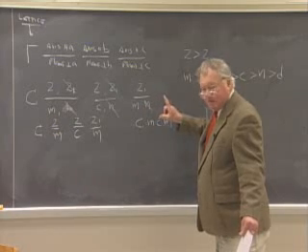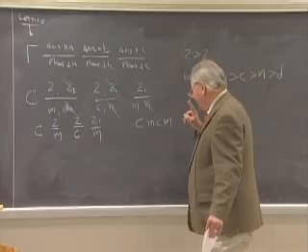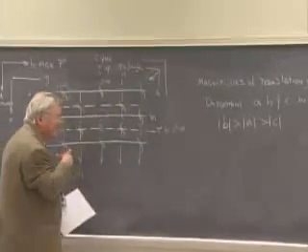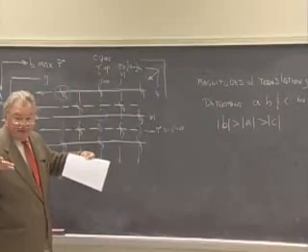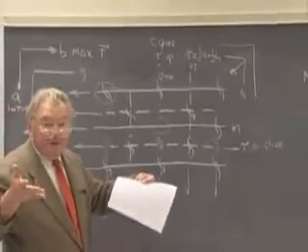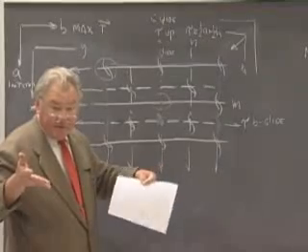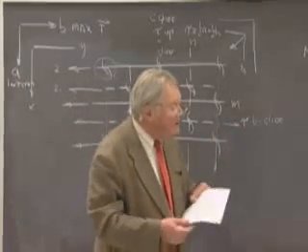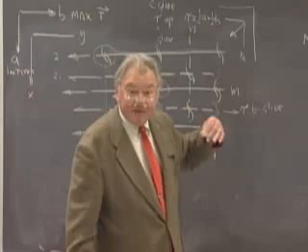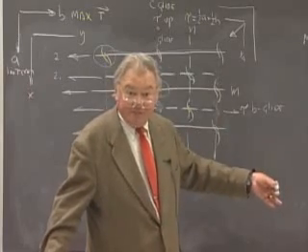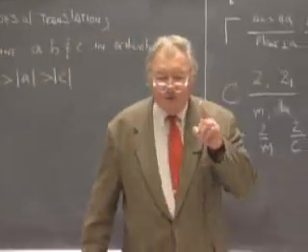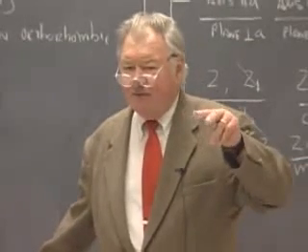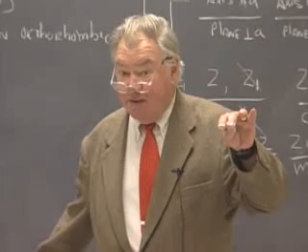Is it possible that two space groups could have exactly the same 3 symbols in the short form? And the answer is no, because if you think about it, you start with a lattice type. If you put a mirror plane in one orientation, a mirror plane in the other orientation, that really is all you have to specify in order to determine every other symmetry element that's present. You simply combine those operations, and you find that when you've taken these symmetries and rotations and combined them with the lattice translation, it comes out to one and the same, a unique result. So your question was, what happens if you take another 3 symbols? You end up with the same result. 3 of them really are enough to specify what the group will turn out to be. Okay.